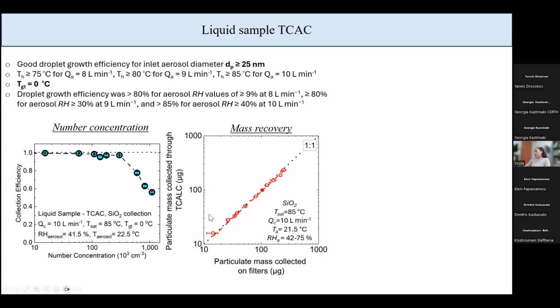This mass was first extracted on a filter through vacuum filtration, and then I used the mass balance to obtain the weight of it. And this is the correlation of these two techniques. We see a perfect agreement between the two techniques, which shows that we can use the liquid sampler the same way as we use the filter when we need to collect the sample in a liquid suspension.